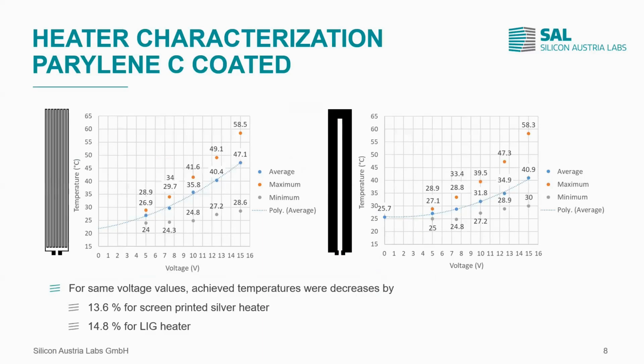So the same thing was then done after the Parylene-C coating. And as we can see here, the average temperatures decreased by 13.6% for the screen printed heater and 14.8% on average for the LIG heater. Why is this happening? Of course, if you put a coating on top of the heaters, what is happening? You add thermal mass, and this also needs to be heated up. And the second main factor here is that the Parylene-C coating works as a shielding for the thermal radiation.